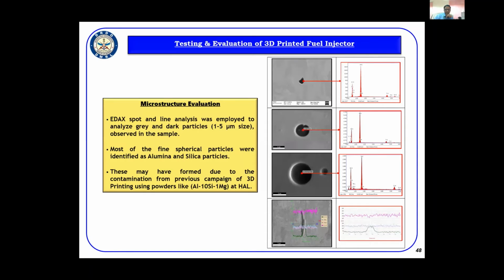Then we went back to the records to see what the reason may be. One of the conclusions is that these might have formed due to contamination from the previous 3D printing campaign using powders like Al-10Si-1Mg at HAL. So it is also very important to plan the campaigns in a systematic manner, where complete cleaning of the machine is taken up before starting a campaign with any other material. This is one of the aspects everyone has to look into when working on the same machine using different materials. This type of impurity will be dangerous with respect to the life of the 3D printed component.